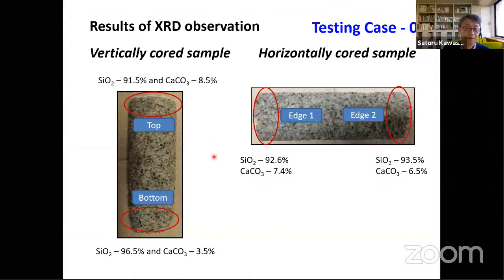Then we evaluated by XRD test, XRD observation. The left side indicates the vertically cored sample case, and the right side the horizontally cored samples. On the left side, vertical cored samples, as I said, this sand consists of silica, mainly more than 90% silica on the top side. On the other hand, the bottom also mainly consists of silica.